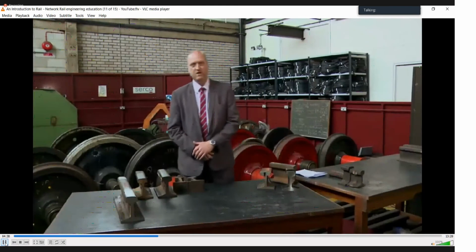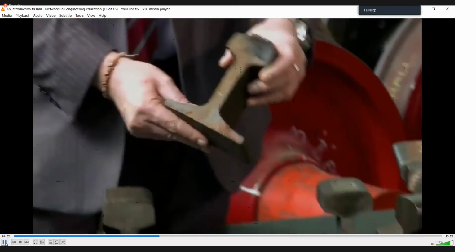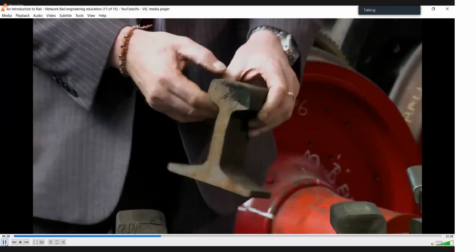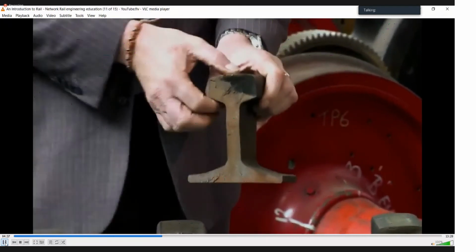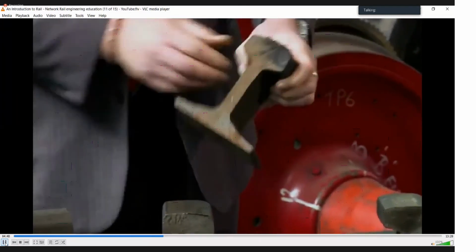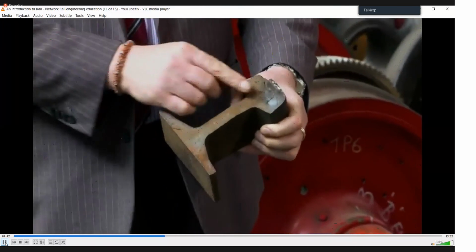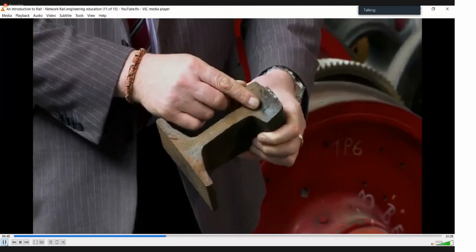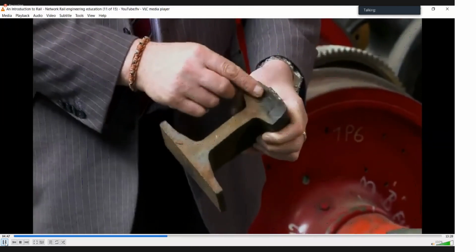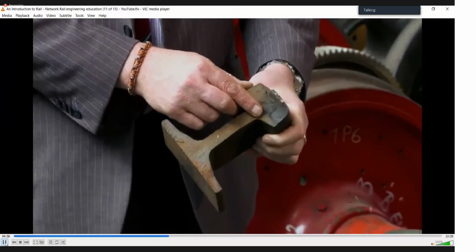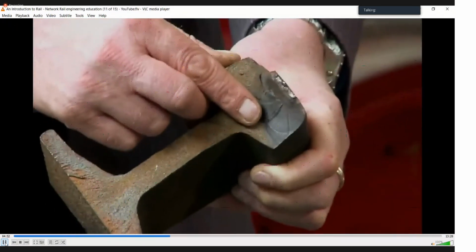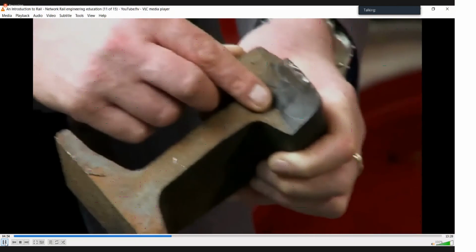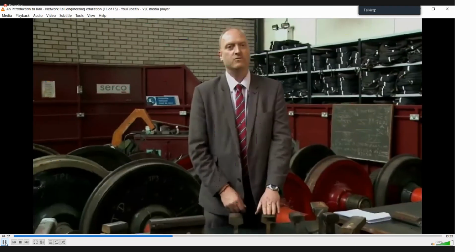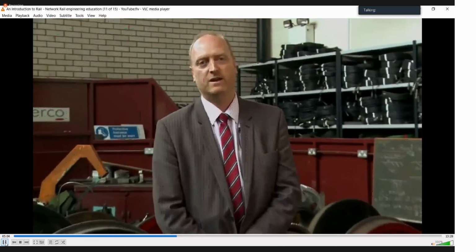There's a few examples of rail we have here. This sample here shows a fatigue crack which is initiated from the surface of the rail. It's caused by the repeated passage of wheels over the surface, which will initiate small cracks, and then through fatigue, this will grow progressively over a long period of time. The discoloration and classic markings you can see here are a result of the surface becoming oxidised and corroded where it becomes exposed to the elements. Surface damage and rolling contact fatigue is our biggest cause of problems. It accounts for something like 50 to 60% of all defects we remove from track each year.